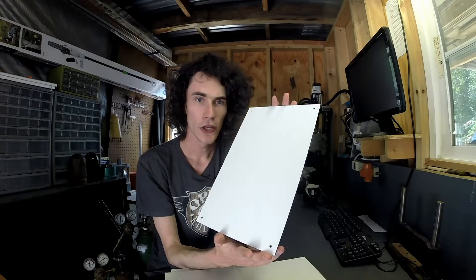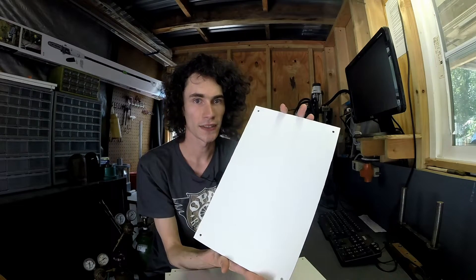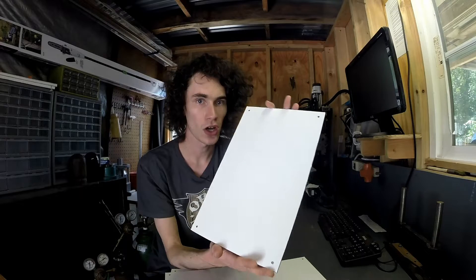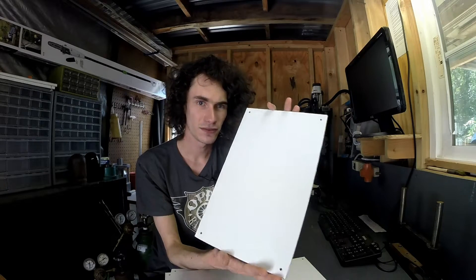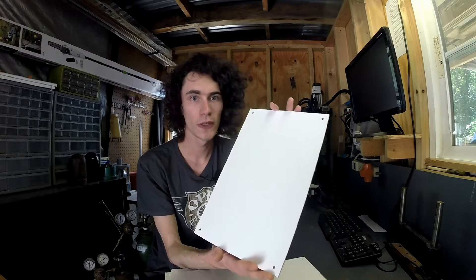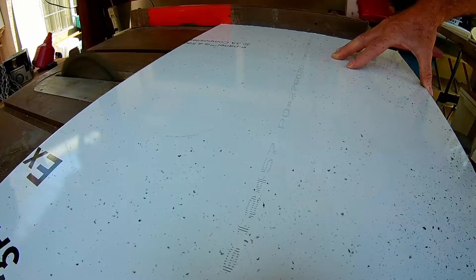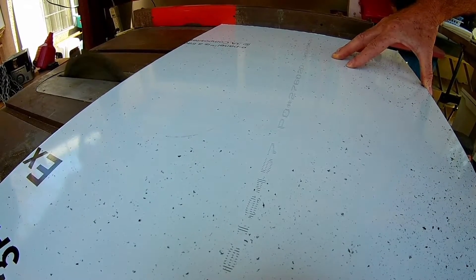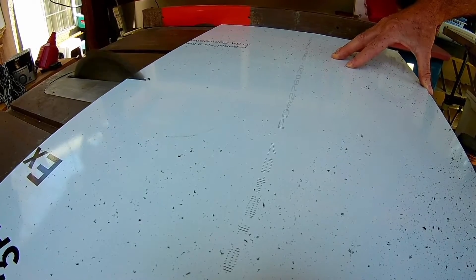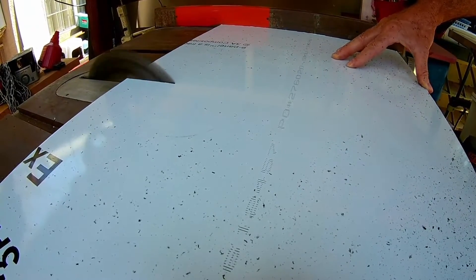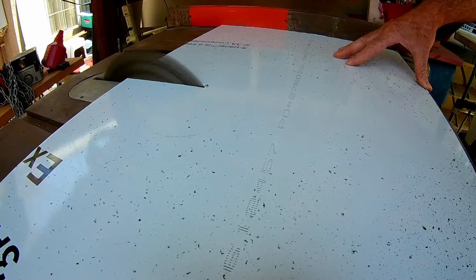Drilling holes is easy. Do keep in mind, though, that you do have the soft plastic core in there, so when you're feeding it through a saw, don't dilly-dally and don't run a dull blade. Neither the aluminum nor the plastic like that, but overall it cuts very easily. I would recommend, though, use a sharp table saw blade, one probably that has more teeth than less. My dad's table saw blade is somewhat coarse and a little bit on the dull side. It cut fine, but it definitely left slightly rougher than desired edges, but for this, it's perfectly fine.